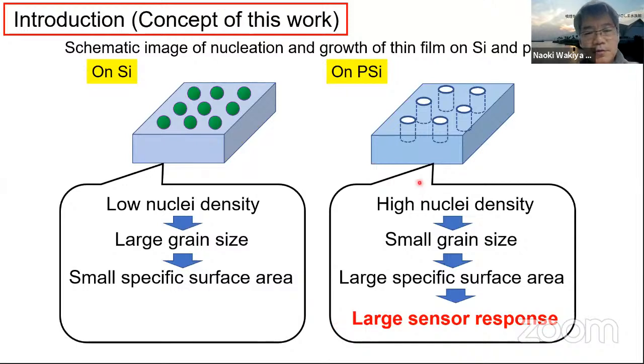But if we use porous silicon as a substrate, since there are porous structures, many nuclei will be formed. So high nuclei density is expected. And grain growth is limited, so the grain size is expected to be small. So a large specific surface area is expected. So we think that by using porous silicon as a substrate, a large sensor response will be realized.